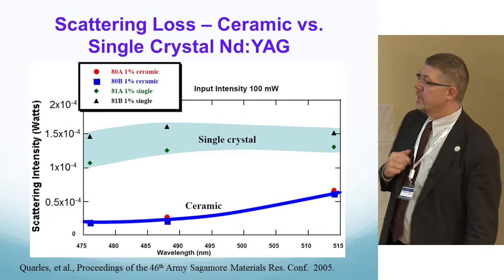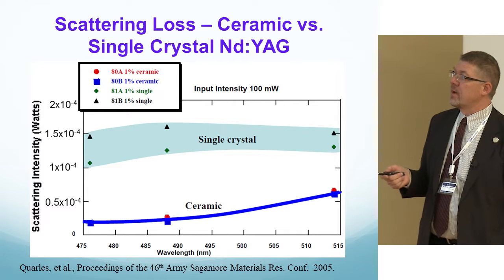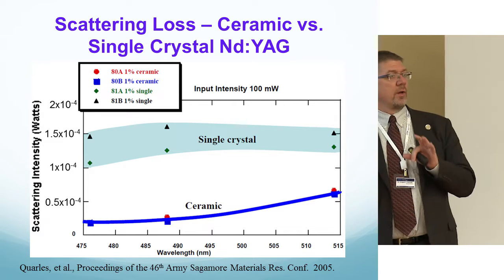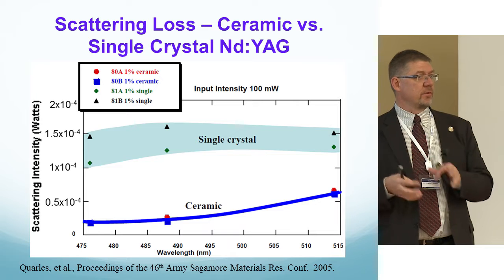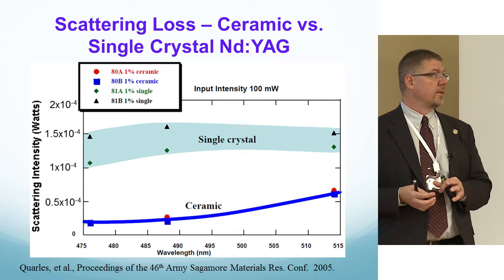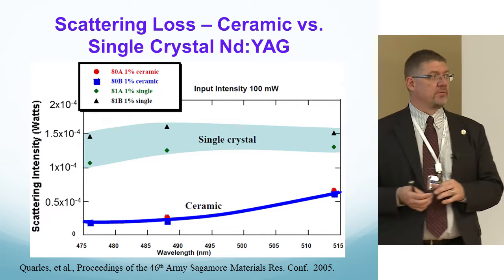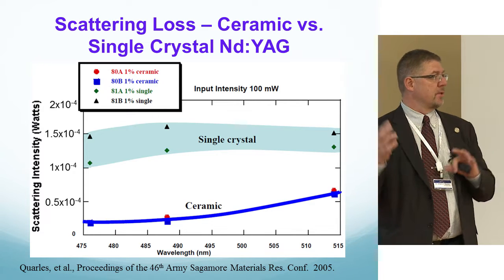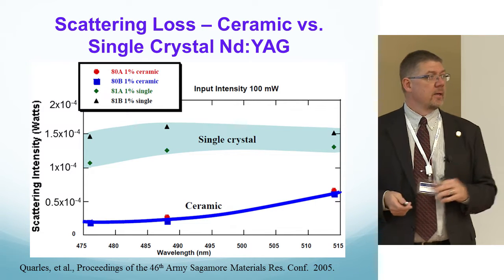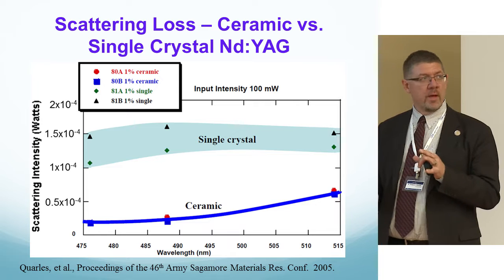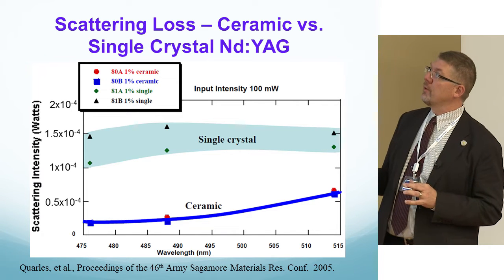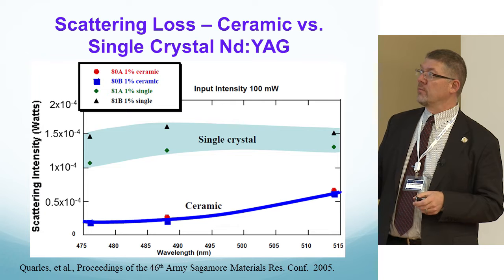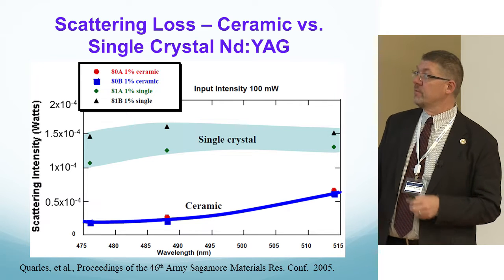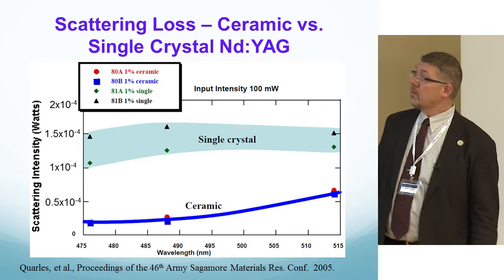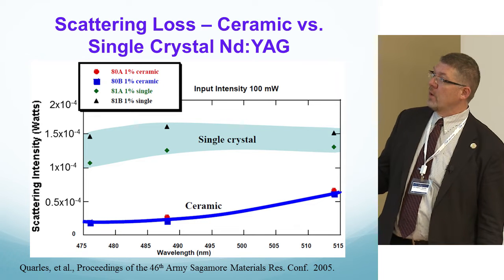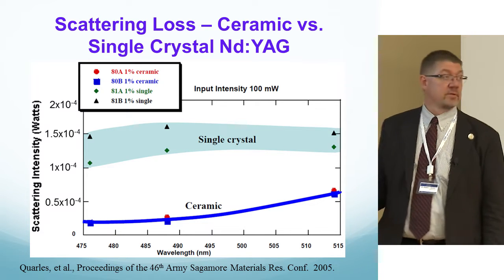Some of the early work that we did, I did a paper back in 2005. Our facility was growing the largest amount of single crystal neodymium YAG globally. There were about 8 or 9 facilities, including facilities in Czech Republic, Japan, China, Russia, that were all growing YAG. And ours we took, and 3 other companies we took as a baseline, and we measured the scattering loss as a function of wavelength on argon lines between 477 and 515. And you can see here that the scattering losses were between 1 and 1.5 times 10 to the minus 4.